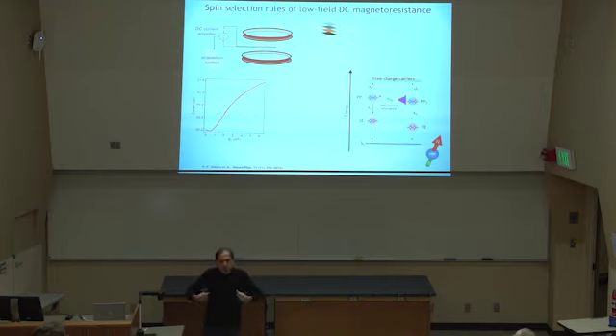What happens is charge carriers find pairs, which eventually will recombine. But before they do this, they form intermediate pairs. And these intermediate pairs happen to be pairs of paramagnetic states, 2 spin 1/2, electrons and holes, with weak spin coupling, so low exchange and dipolar coupling, and also very weak spin-orbit coupling, so electronic transitions require spin conservation. And what that means is you build in the steady state densities of different spin manifolds. Triplet states, singlet states, but because of spin conservation, Pauli exclusion principle, the decay of these pair states is much, much faster for singlet states than triplet states.